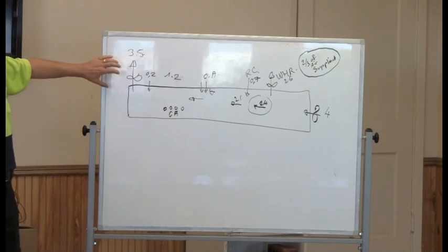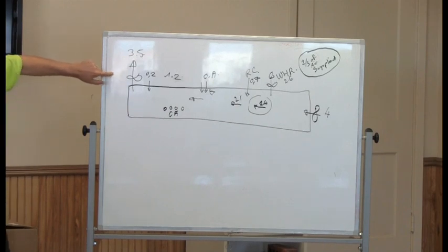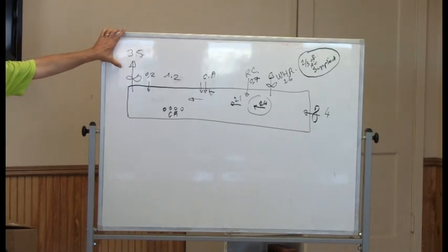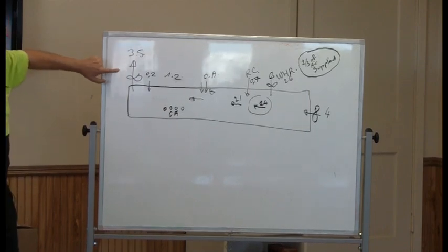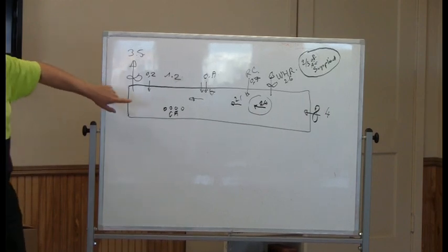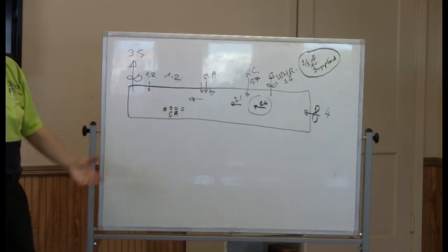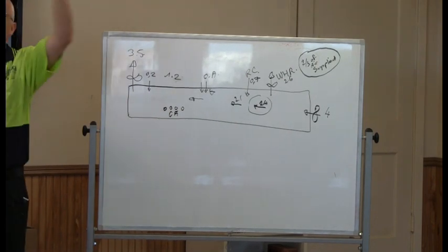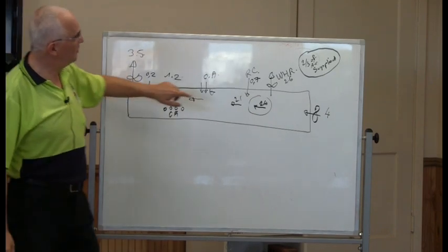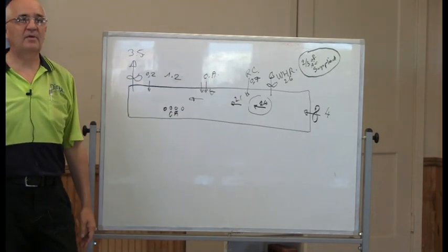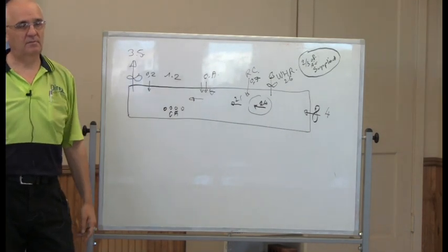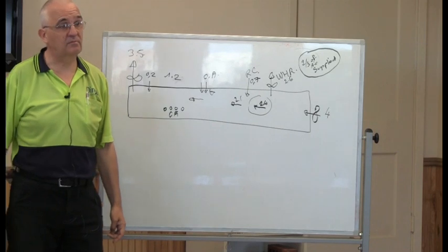So there is not one adjustment for the kiln. It's a whole set. And you cannot change, for example, you know, in the old kiln, people were working with that speed, with the tonnage, right? We do now. I mean, we'll talk about that in a minute. We manipulate it. Yeah, but it's good to manipulate that to accommodate the increase of total quantity, because of course you increase your quantity of brick, you maintain your ratio, but the overall quantity increases. But if you increase this without this and that in relation, where is the air coming from? Through the roof, through the undercar, and we're going to talk extensively about roof and undercar because you have problems with that.